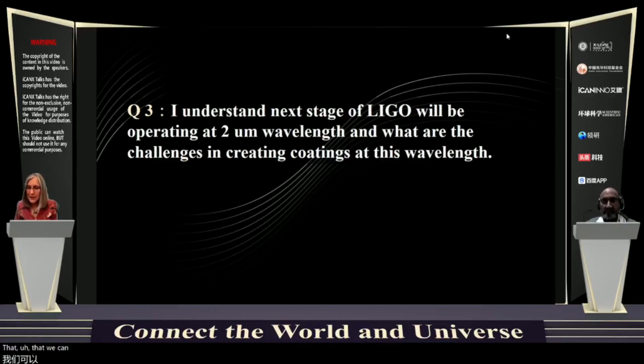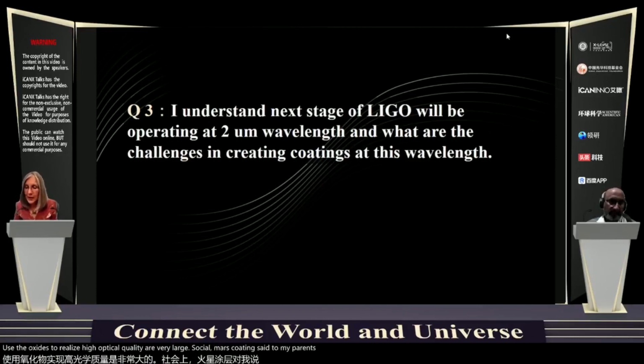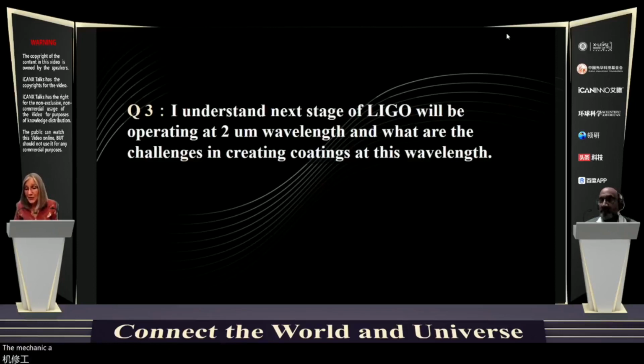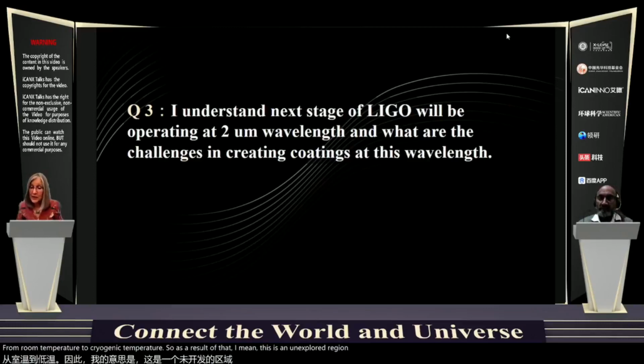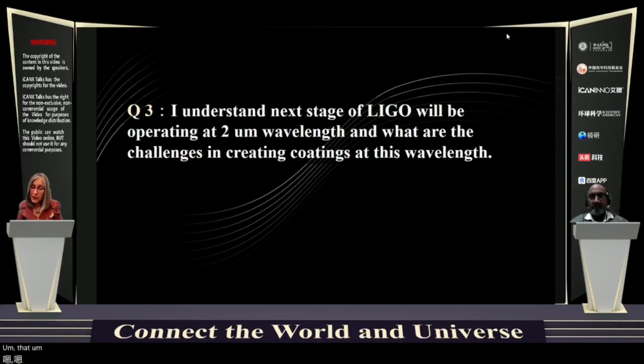that, from the optical standpoint, we can still use the oxides to realize high optical quality, very low absorption loss coatings at 2 microns. However, the mechanical loss properties are different, especially from room temperature to cryogenic temperature. So as a result of that, this is an unexplored regime, and we are going to start working with our collaborators at the Centers for Coatings Research,